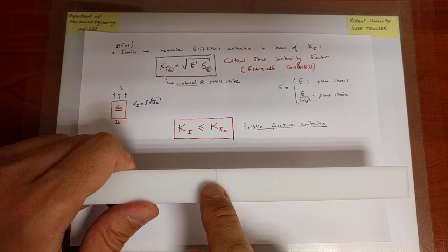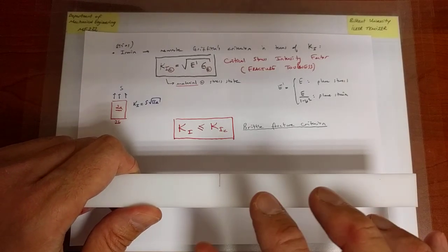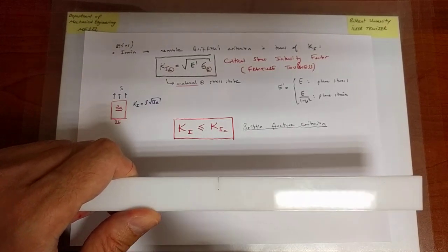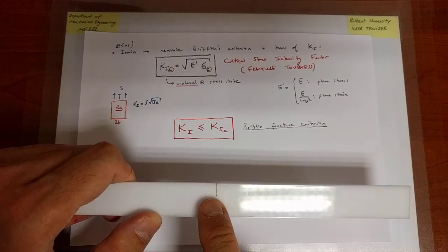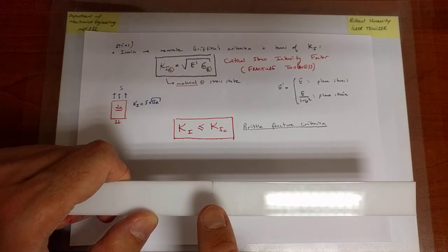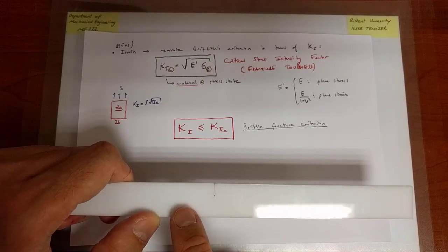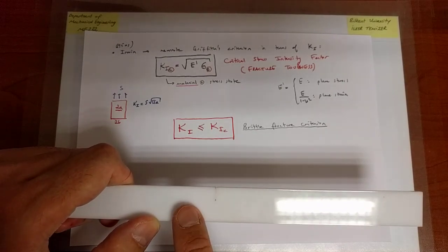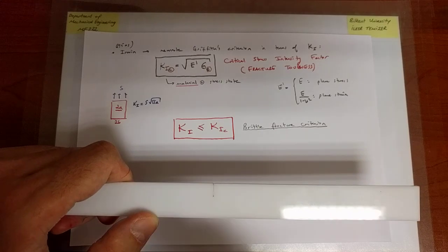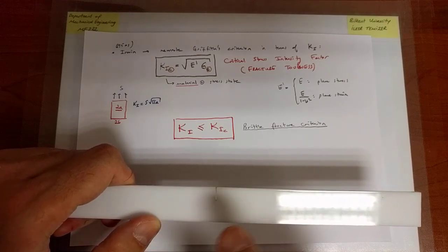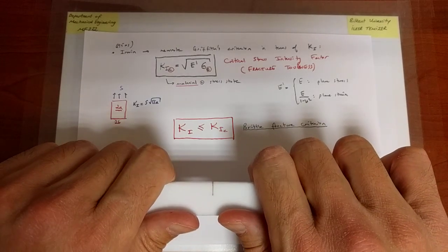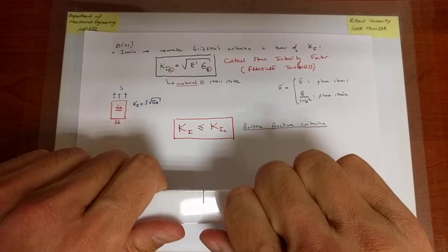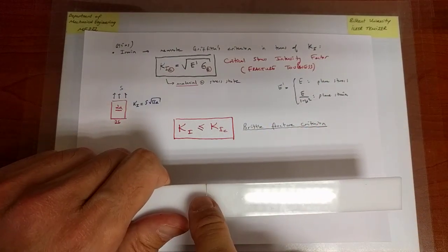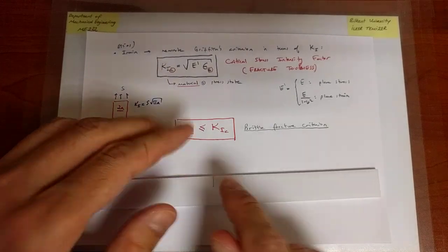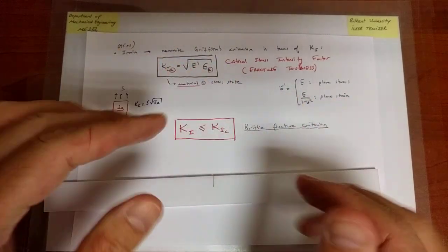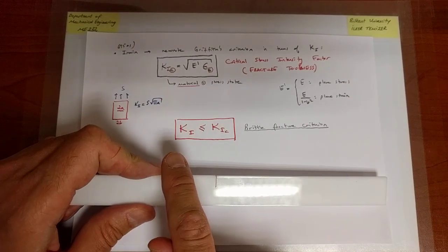Now remember, earlier we said that mode 2 is a type of loading that is naturally induced by bending, but mode 2 had to do with sliding of the surfaces. What you have to keep in mind at this stage is bending does not necessarily always make the surfaces slide with respect to each other. In this case, when I bend in that direction, I'm going to actually try to open the surfaces of the crack. I'm going to try to move them like this. So that's the opening mode, and hence mode 1 loading.